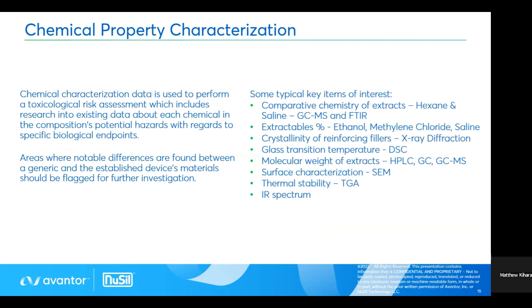Chemical characterization data is used to perform a toxicological risk assessment, which includes research into existing data about each chemical and composition's potential hazards with regards to specific biological endpoints. Again, areas where notable differences are found should be flagged for further investigation. Some typical items of interest for chemical property characterization are percent extractables in ethanol, methylene chloride, and saline. Comparative chemistry of the extractables in hexane and saline using GCMS and FTIR.